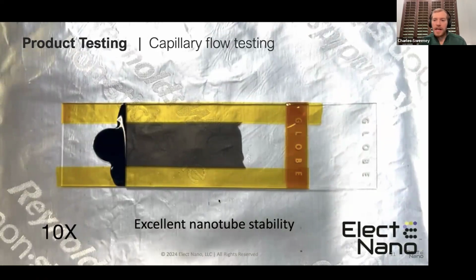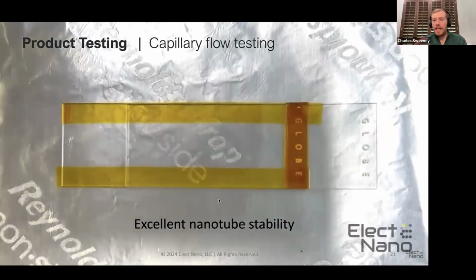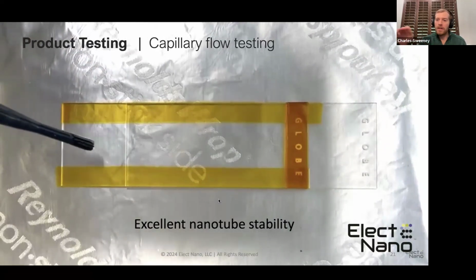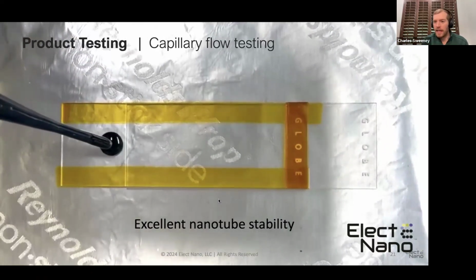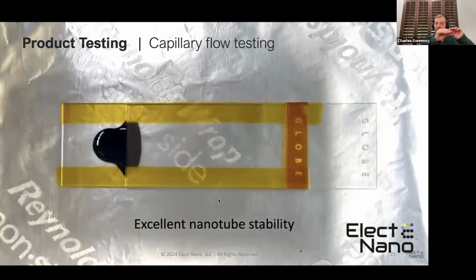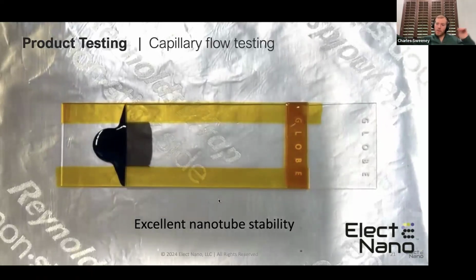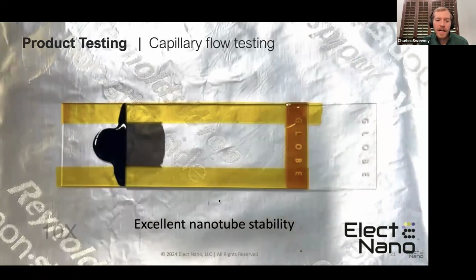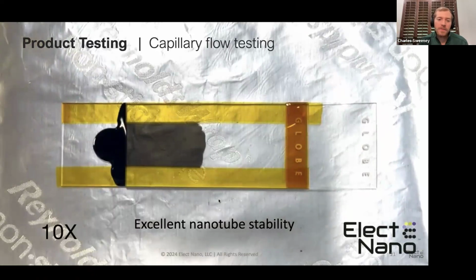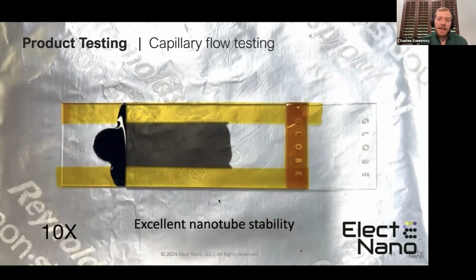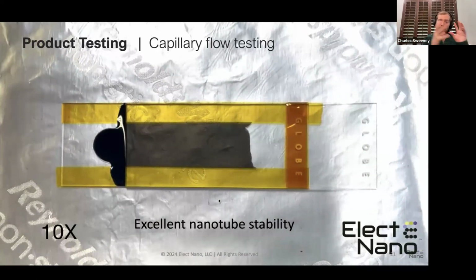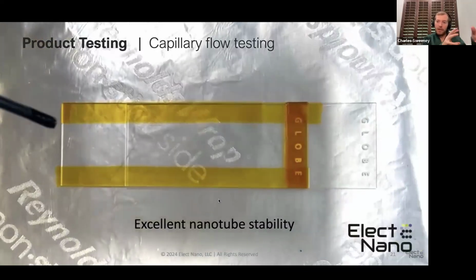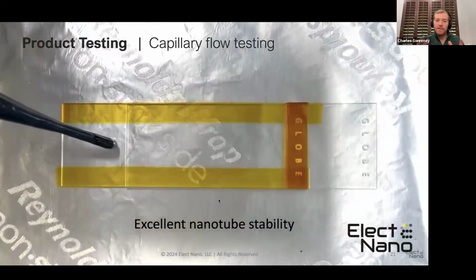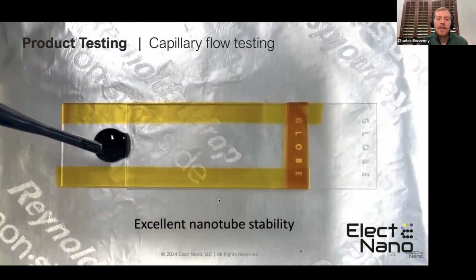I could see this having applications in resin transfer molding or other carbon fiber layup operations where you're trying to get epoxies to wick and wet out through carbon fiber epoxy or carbon fiber laminate systems, because you want the nanotubes to stay with the resin and not just get filtered out or crash out of your epoxy during the curing stage.